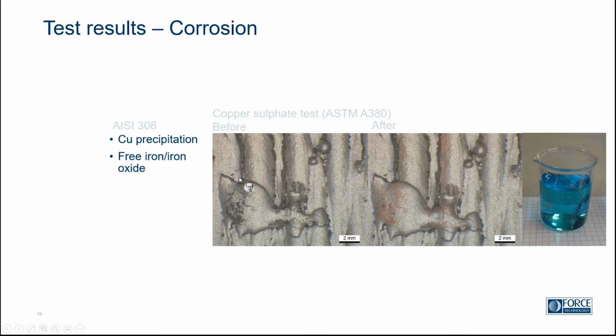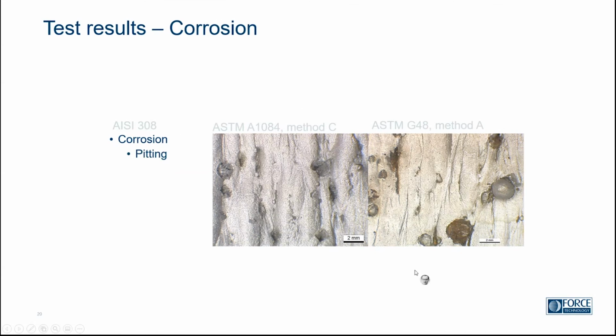So the idea of this copper sulfate test is that if you have free iron or iron oxide, which is not able to passivate and protect the steel, you will get copper deposition, which is what we see here. Looking at the before, we have some dark areas, which I would naturally suspect to be oxides left over from printing, or it can also depend on your cleaning process whether you remove these or not. But we see that we get this slight copper coloring on a lot of these parts, which indicates that we don't have the necessary protective oxide here.